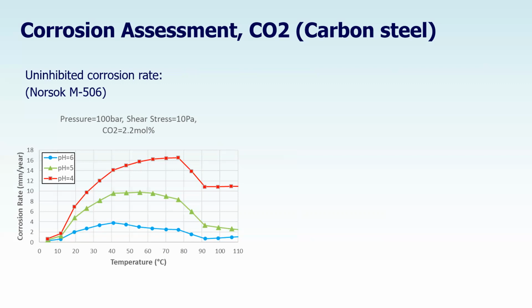Apologies. Just to highlight, our pipeline maximum operating temperature is 110 degrees C. However, since the temperature profile is not known at this stage, we selected 60 degrees as the worst case scenario. What does it mean? We have to inject inhibitor if we would like to use carbon steel.